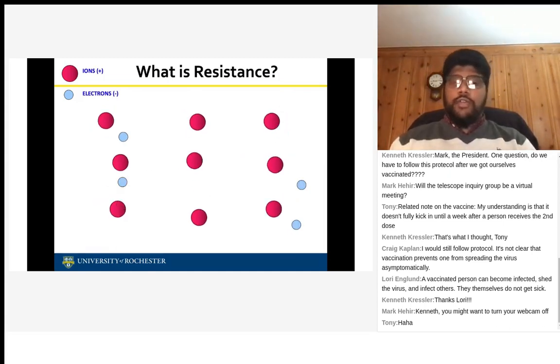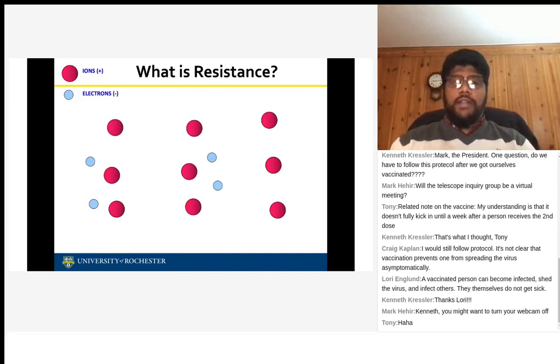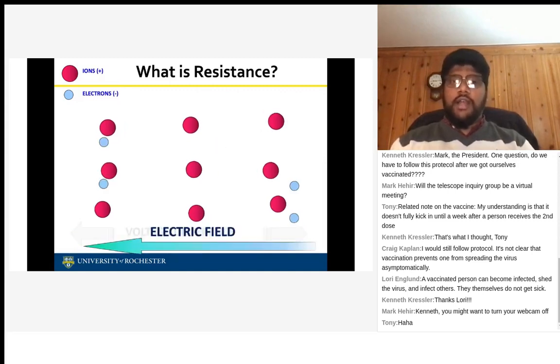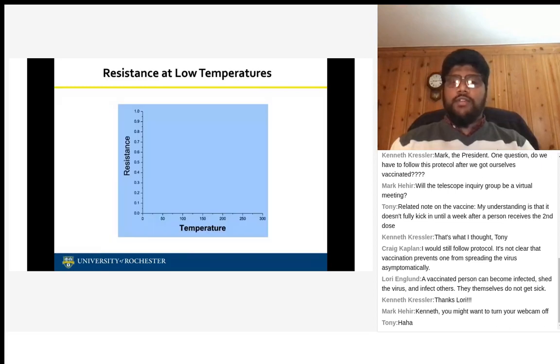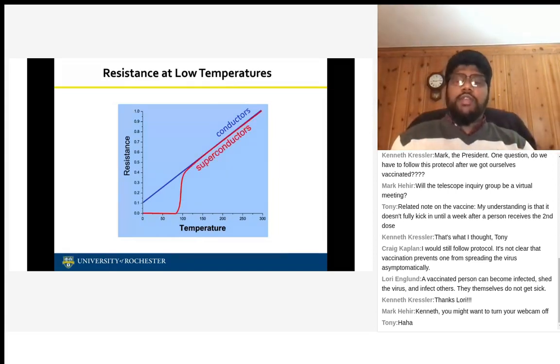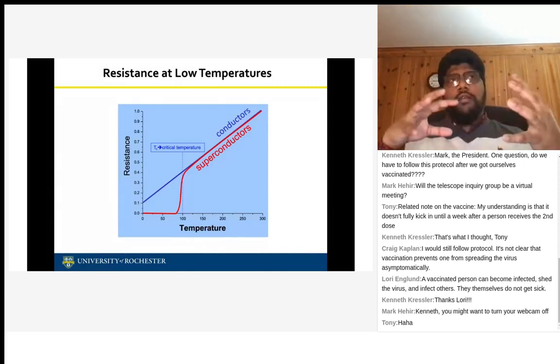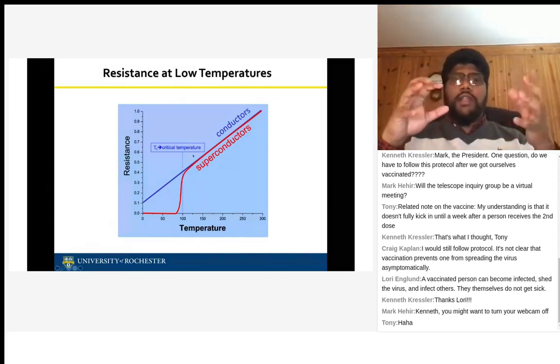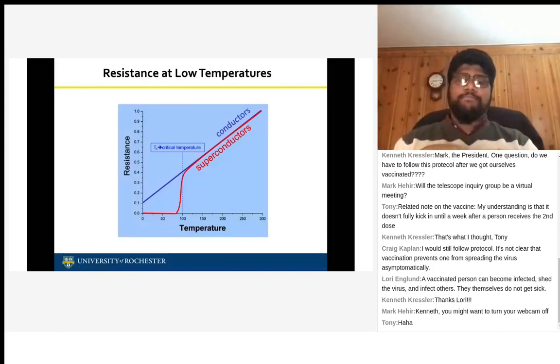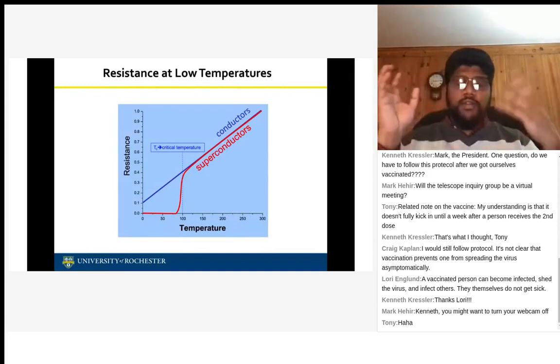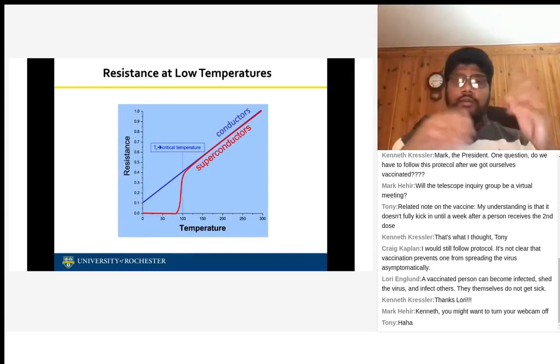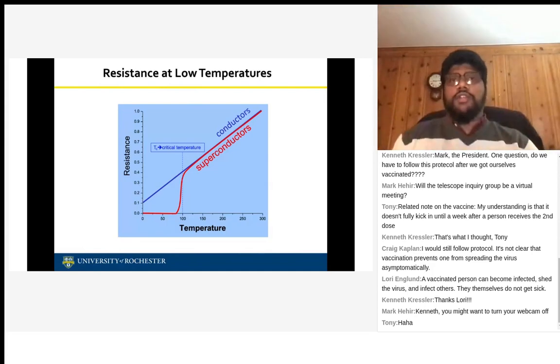Just to show you what happens, if you take different materials, say a conductor, you will have a finite resistance when you cool it down. If you take a superconductor, you see that the resistance goes to zero at some temperature. We call this the critical temperature. The problem is that all these superconductors superconduct at really low temperatures, 20 Kelvin, 40 Kelvin, in Fahrenheit around minus 400 degrees. It's not in a usable range.